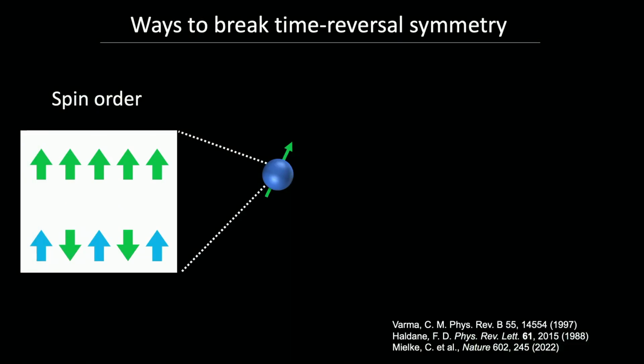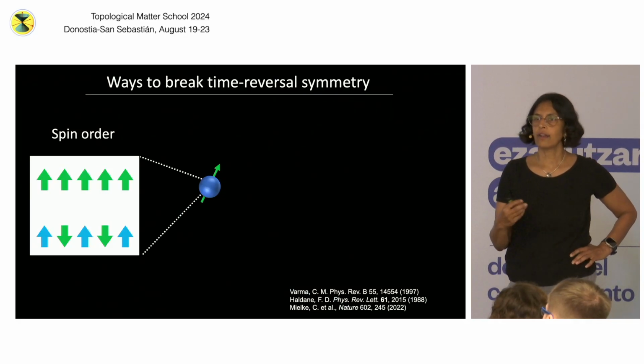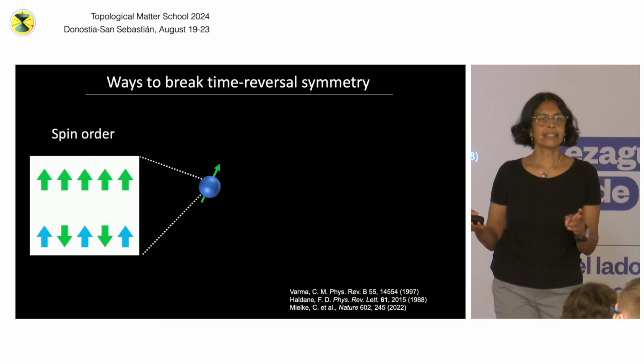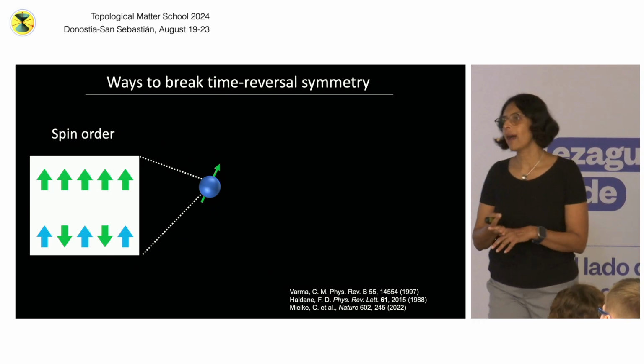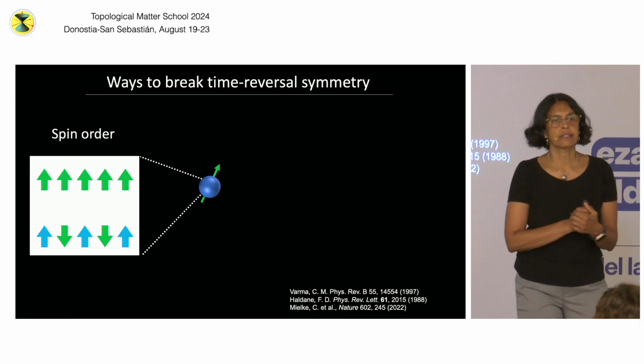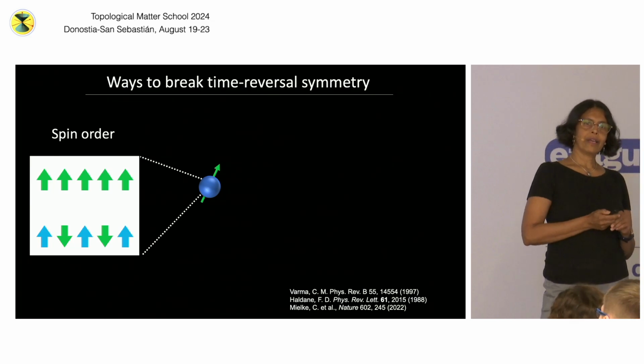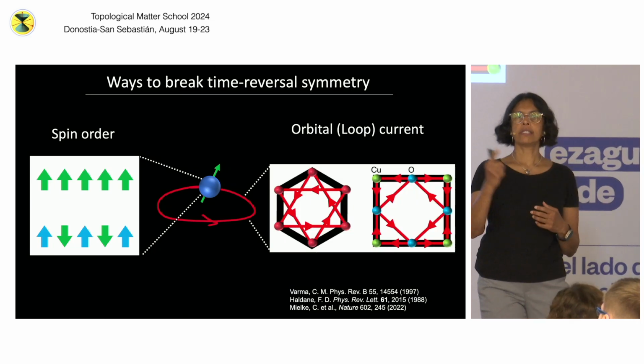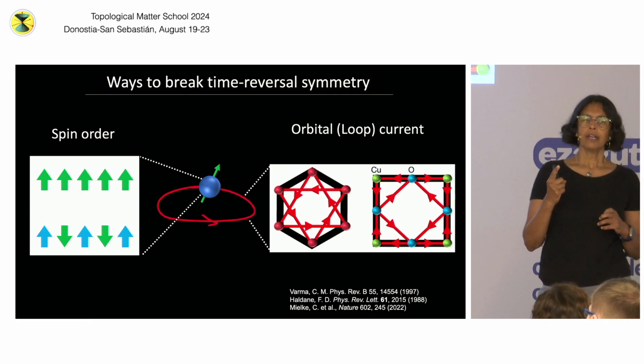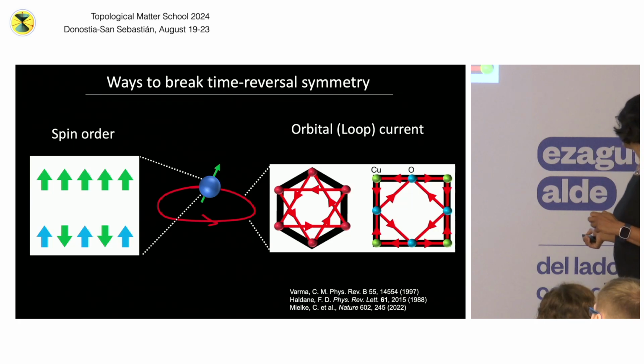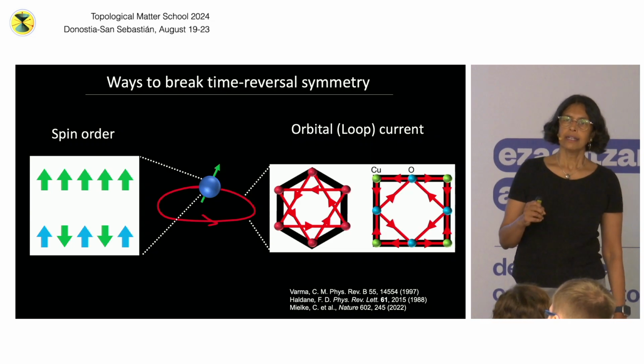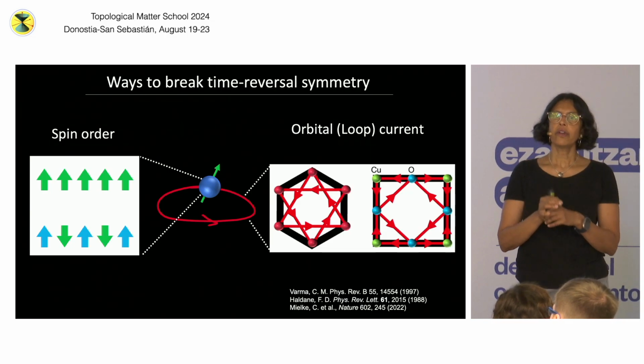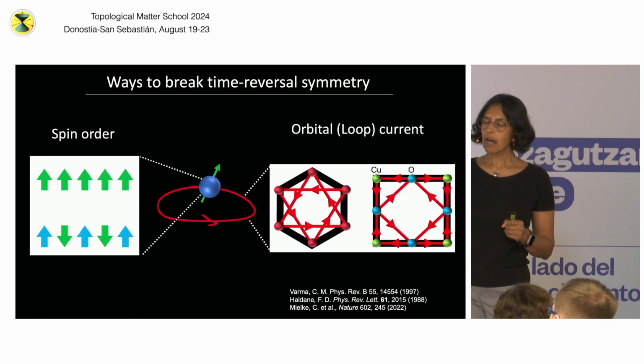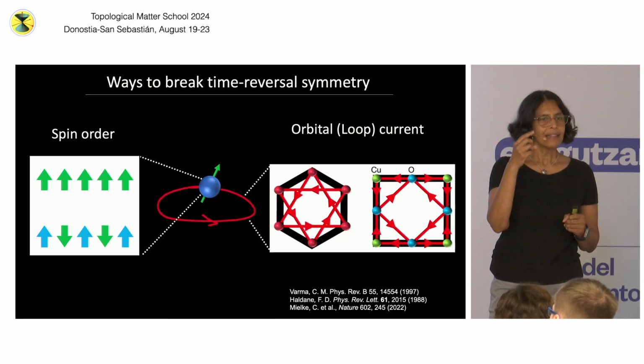Okay, so time reversal symmetry. We're familiar with one way to break time reversal, and that is to have an ordered set of moments. So if you have localized spins in your system, and they order in any way, ferromagnetically or even antiferromagnetically, then you break time reversal symmetry. However, there is another way to break time reversal. We're very familiar with this. You know that if you have circulating currents, you can break time reversal symmetry. However, in the 90s, in the context of the cuprates, Chandra Varma, Haldane, and a bunch of other people proposed that in a solid state system, you can have a spontaneous generation of currents on a very small length scale, on lattice length scales.